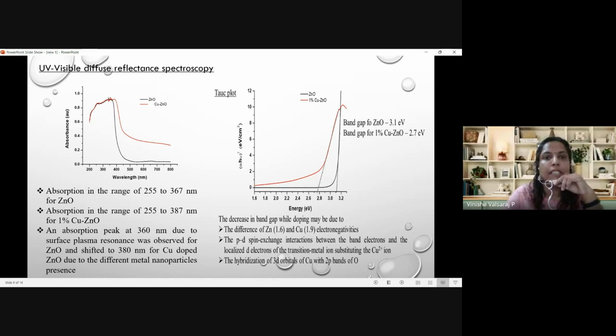UV-visible diffuse reflectance spectroscopy was used to characterize the optical property. Here you can see an absorption range of 255 to 367 nanometers for ZnO, while 1% copper ZnO has 255 to 387 nanometers, and there was a peak at 360 nanometers in the case of ZnO. That is mainly due to the surface plasmon resonance, and that is shifted to 380 nanometers in the case of copper doping. This surface plasmon resonance peak is shifted mainly because there are 2 types of metal ions present in it.